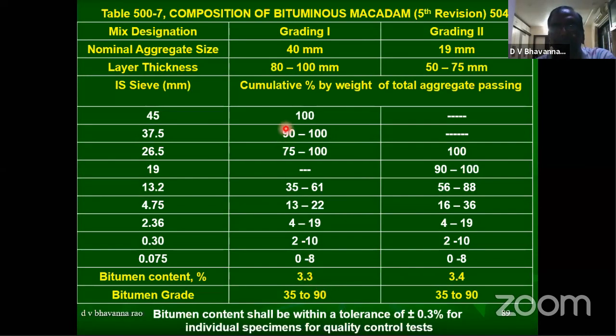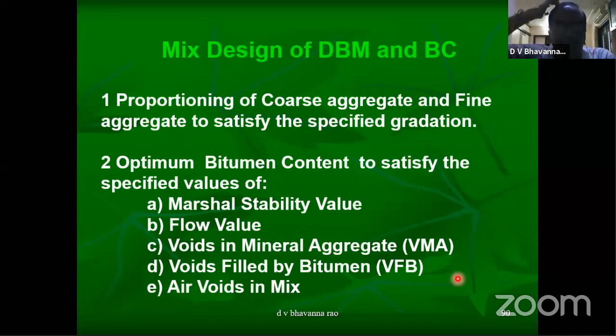Bitumen content is 3.3% for 80 to 100 mm layer, and for 50 to 75 mm layer, 3.4% bitumen. Now, this mix design of DBM and BC: DBM and BC are controlled mixes. We have to design for Marshall stability value, flow value, voids in mineral aggregates, voids filled by bitumen, and net air voids in the mix. For these 5 items, we have to design the bituminous mix for DBM or BC.